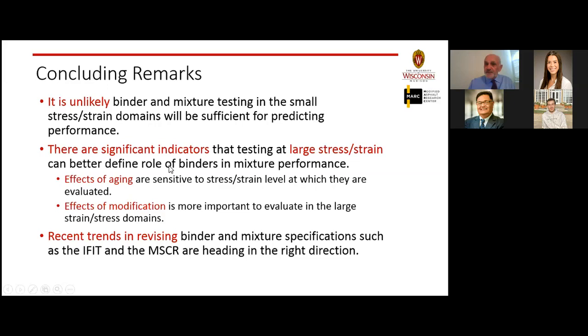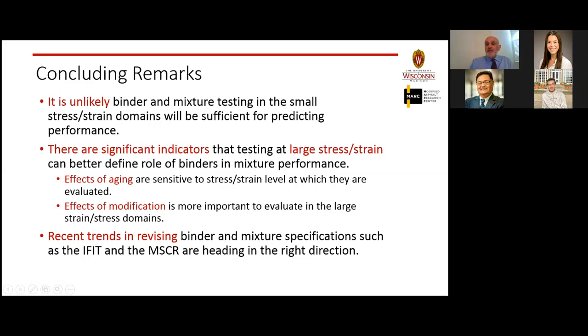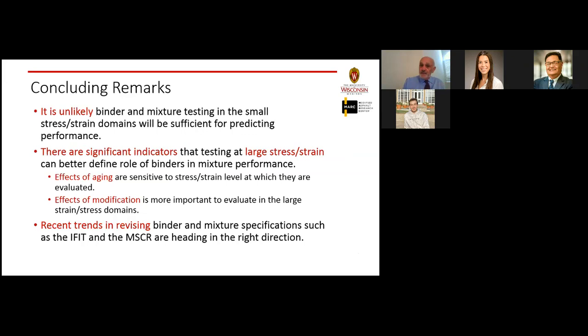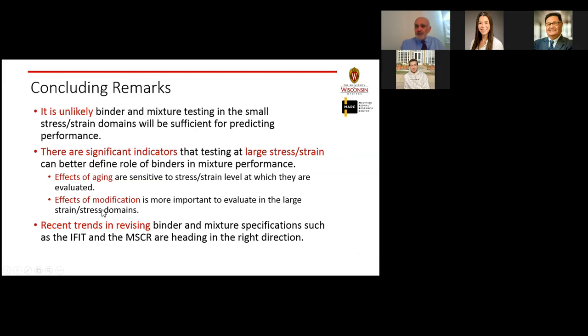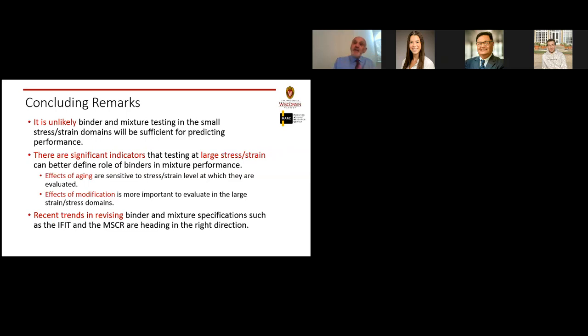I already showed you an example, effect of aging. Anyone today that can tell me, well, I did aging and my fatigue results are going higher, and ask me, do you think that's logical or did I do something wrong? I have an answer, that probably they did not take care of the actual strain level, and that in fact, if our pavements can perform at very small strains, it could be that aging can be helpful for us. Also, if you're looking at asphalt modification, honestly, if you bring me data with G-star over sine delta, it doesn't mean much because I can see my results and my data as well as many, many other research centers showing how much different modification can improve things if you go to the large strains.